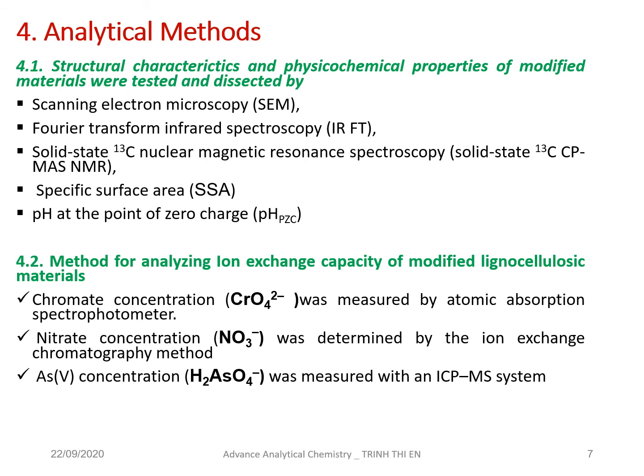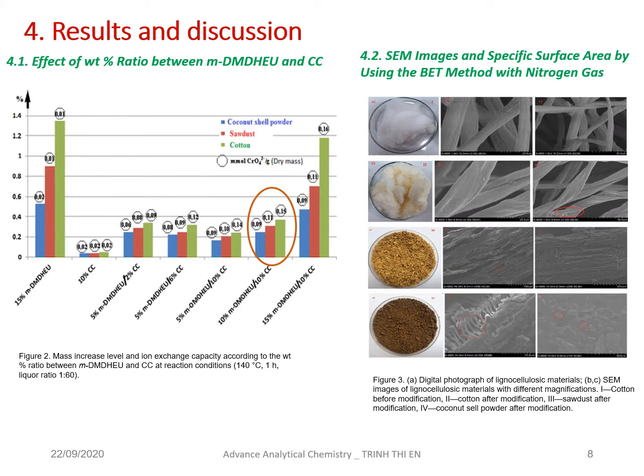It is referred to as SEM, or Fourier transform infrared spectroscopy (FTIR), solid-state 13C nuclear magnetic resonance spectroscopy, and specific surface area, because it's a material, and the pH at point of zero charge, or pHPZC. And the methods for analyzing the ion exchange capacity of the modified cellulose material include: chromate concentration was measured by atomic absorption spectrophotometer, nitrate concentration was determined by ion exchange, and arsenate concentration was measured by an ICP-MS system. And now the results and discussion.